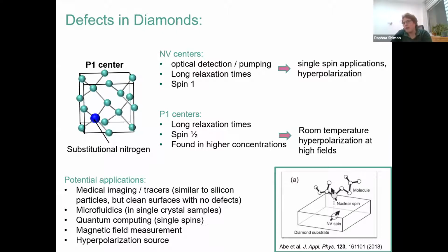The problem with NV centers is that the polarization depends on the angle of the NV center with respect to the magnetic field. And so sometimes it's difficult to polarize at high field, and especially powders. And so that's where P1 centers have a bit of an advantage.